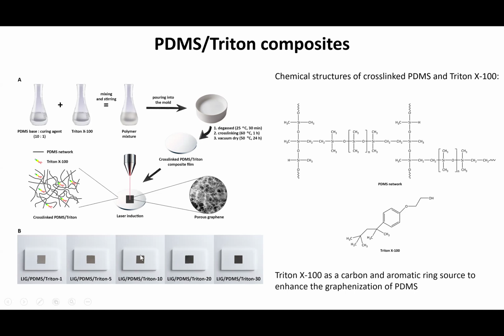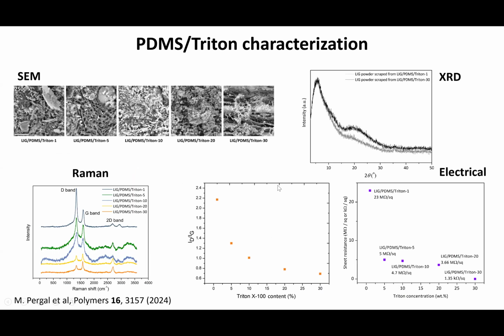And you can see on the bottom these images here. As you add more Triton, the LIG square in the middle, visually you can see already that it becomes darker. So it was our first indication that we're on the right track by adding Triton, that we're probably forming better LIG. But of course, we characterize this with experimental tools. SEM, if you look, they all look good. They all have these pores. And then, for example, XRD, shown in the top right, you have this peak around 23 degrees, which is a graphene-related peak. And you can see that it is enhanced. It is larger if you add more Triton.